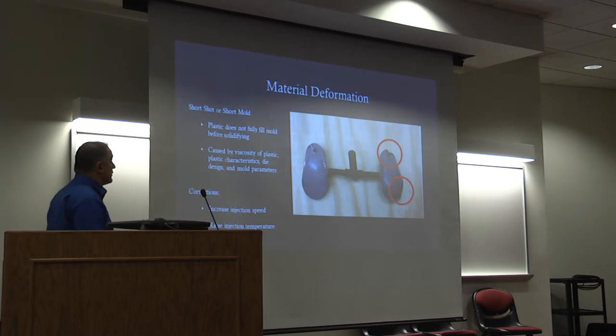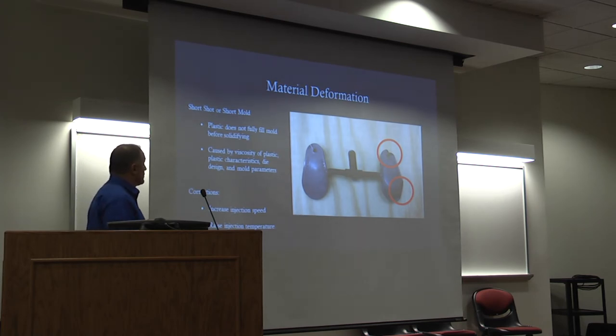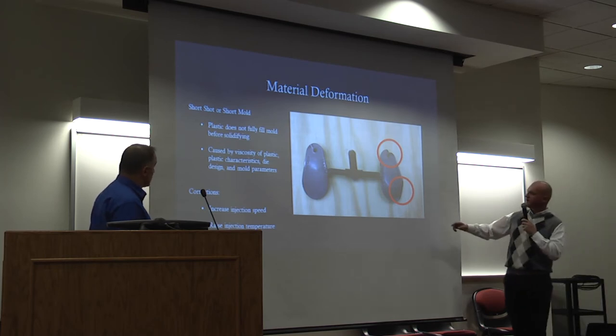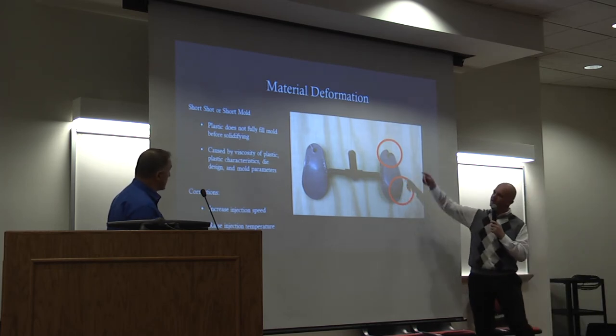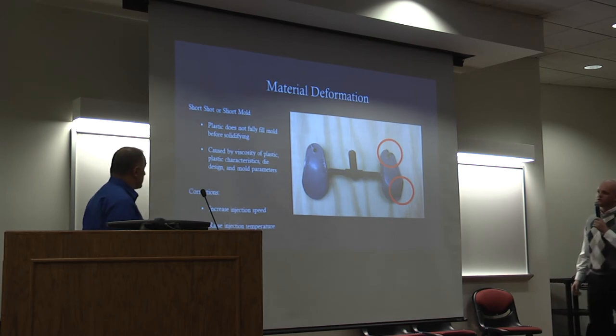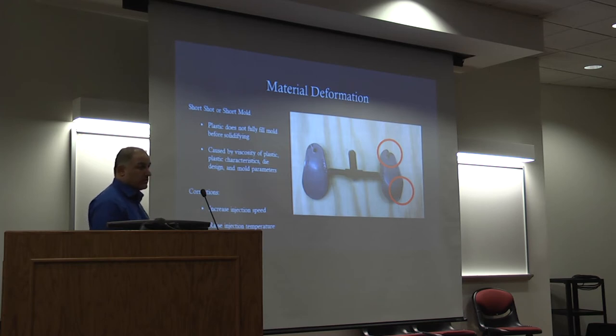So you can see here, we wanted to showcase some of the examples of the material deformation we were getting. In this first picture right here, this is a short shot or a short mold is what this is called. And it's when the plastic doesn't fully fill the mold before solidifying. And it's caused by a number of reasons, some of which are directly related to the temperature control, the viscosity of the plastic, die design and mold parameters, so the temperature of the mold.